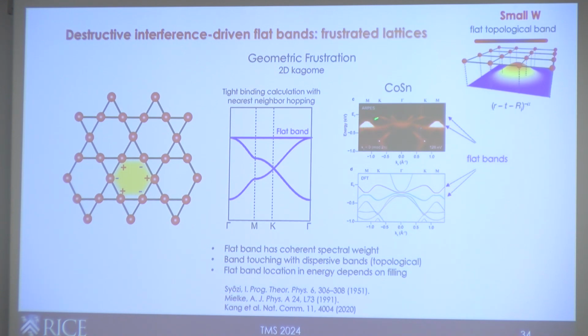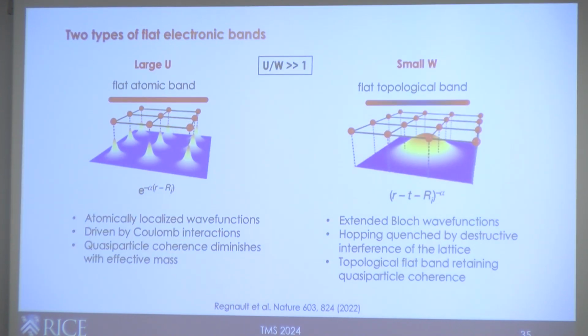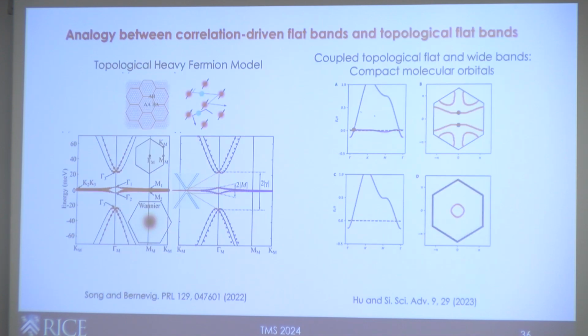CoSn. These are the flat bands, topological flat bands, you get from the Kagome lattice. And you can see that all of these bands, in contrast to the case of U-driven flat bands, have full quasi-particle coherence. You can see them with your eyes. And of course, they could happen anywhere in energy depending on the filling, right? So that's another distinction from the U-driven flat band. So that's the two cases.